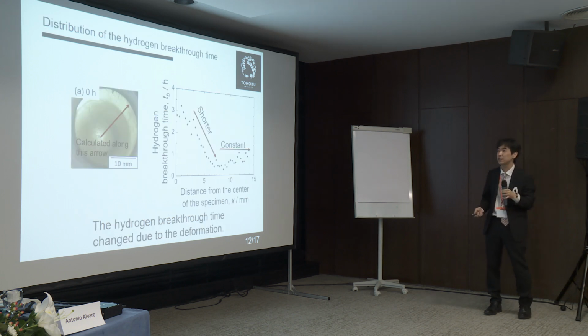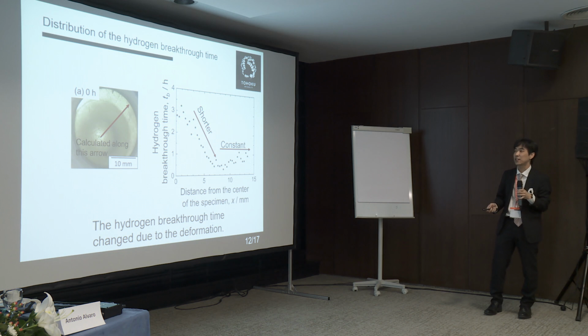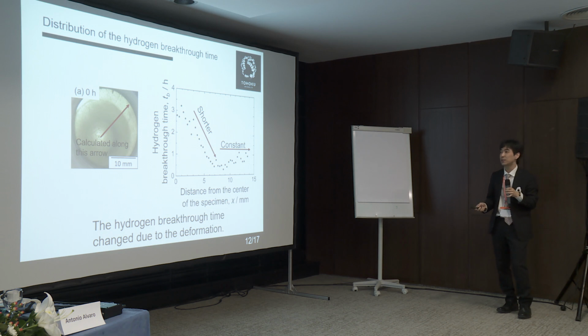Using that data, we calculated the distribution of hydrogen breakthrough time every 300 micrometers along this arrow. This is the relationship between the hydrogen breakthrough time and the distance from the center of the specimen. The hydrogen breakthrough time was long around the center of the specimen and became shorter, and then it became constant.